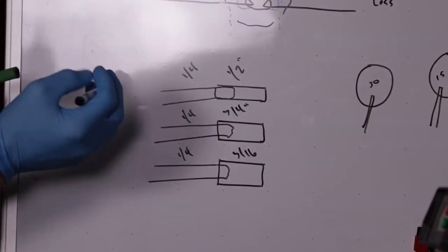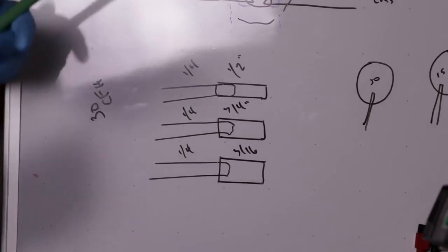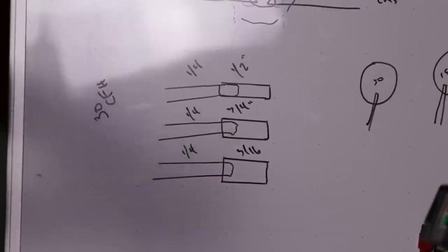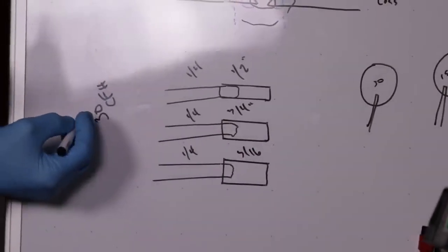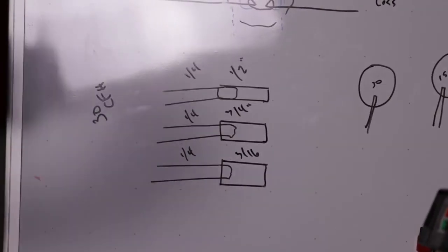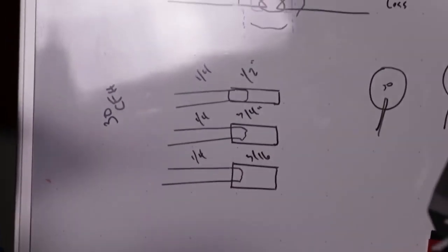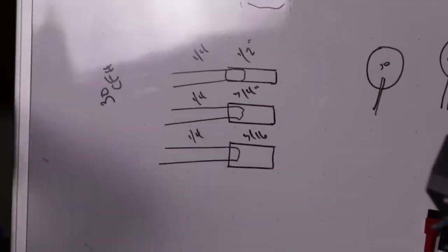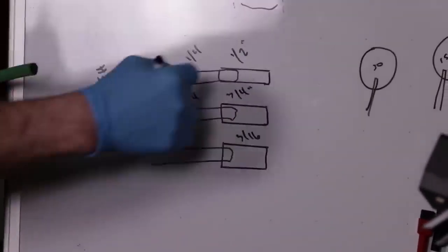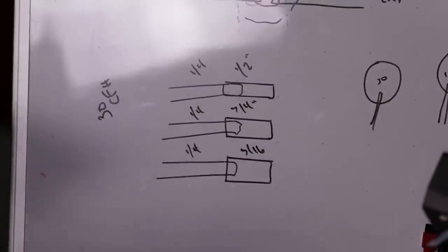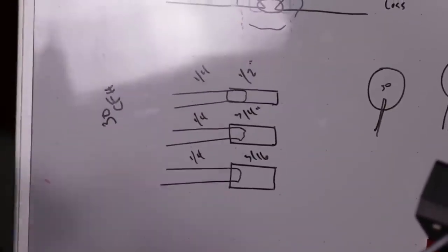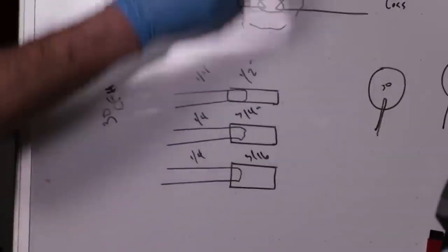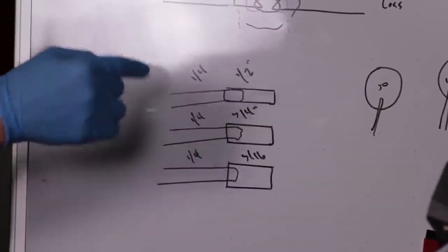So say for example I'm doing a purge, I'm using a 1/4 inch ID hose, and I set my flow rate to 30 CFH. It may be very, very turbulent, and if I'm using a purge monitor to help with troubleshooting, I may be able to detect that my flow rate is creating a lot of turbulence and is drawing and sucking in the atmosphere and influencing my purge quality. So there's quite a lot of variables that go into purging material.